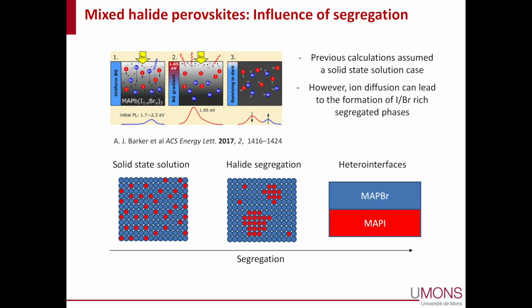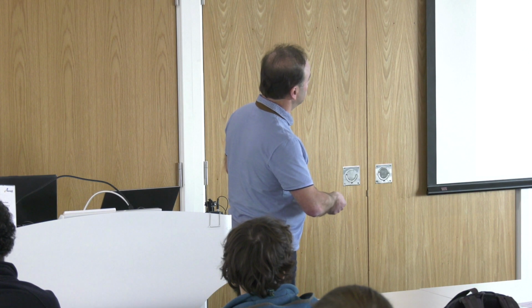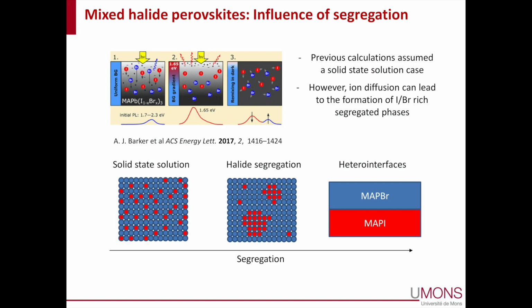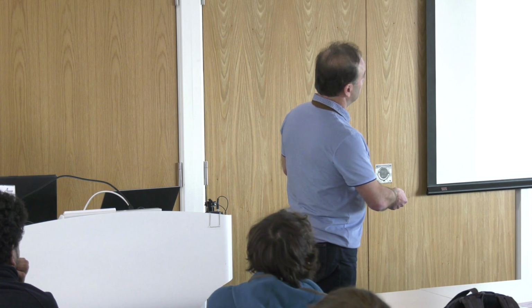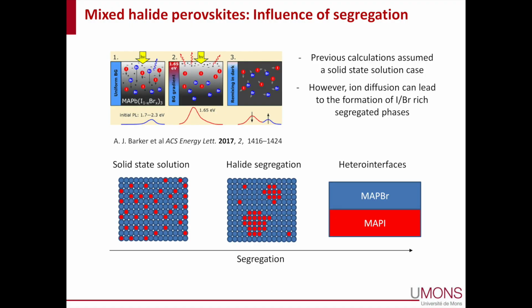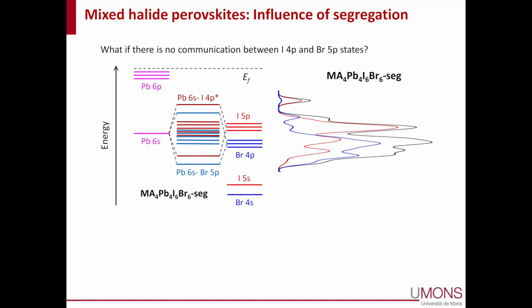Now, of course, the picture that I showed is based on something that we can describe as a solid-state solution, where at the scale that we're exploring, essentially the halides are homogeneously distributed, so randomly positioned. It could well be that in reality there is some degree of segregation, and this configuration would be extremely difficult to model, because that means going to a very large scale system, but we can certainly model a clean interface between the pure bromine and the pure iodine layers. So what happens in a case where you have complete segregation?